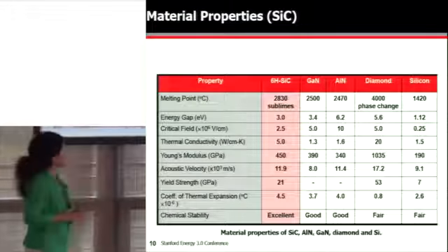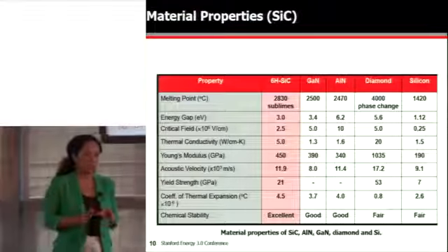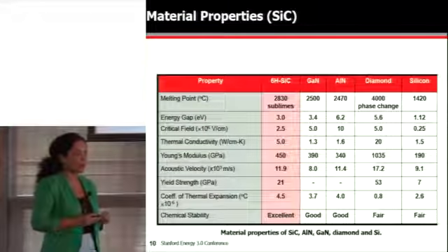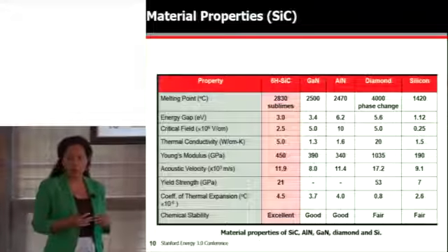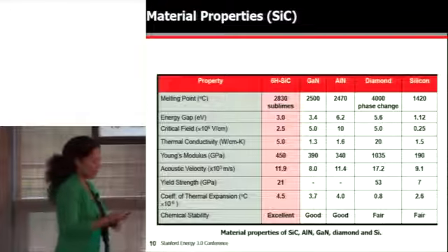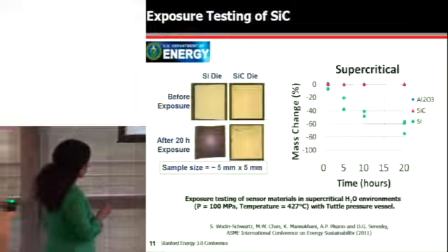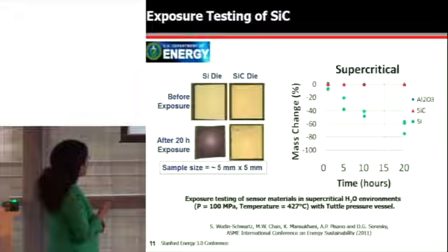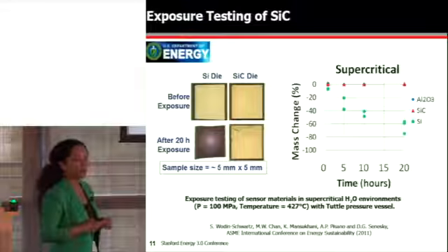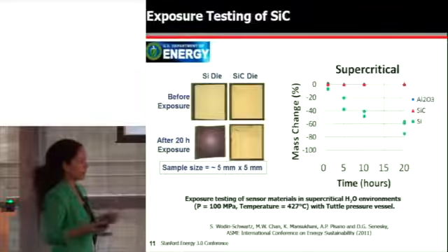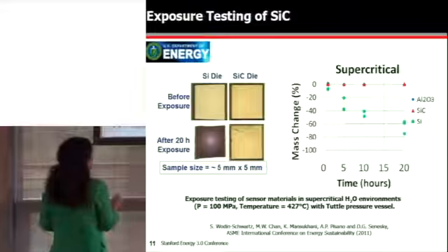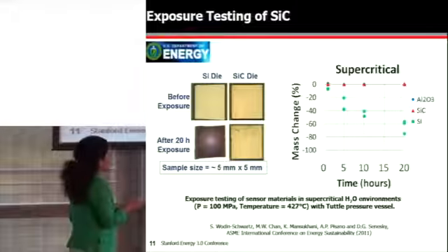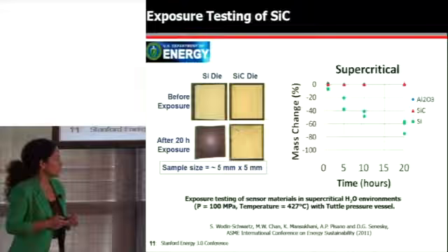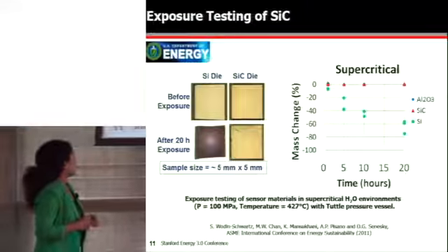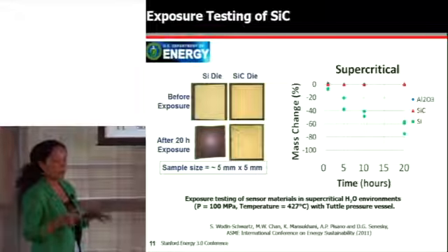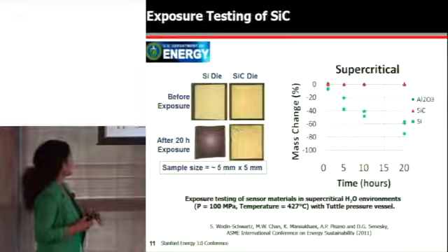Also, the chemical stability of silicon carbide stands out to me. There are no wet chemicals that etch silicon carbide at room temperature, so you can imagine it would operate and function within hot oxidizing environments. So this is some results of exposure testing of silicon carbide within supercritical environments that you would find in a geothermal reservoir, where the pressure is 100 megapascal and temperature of around 427 degrees Celsius. So again, trying to mimic the geothermal wellbore environment experimentally.